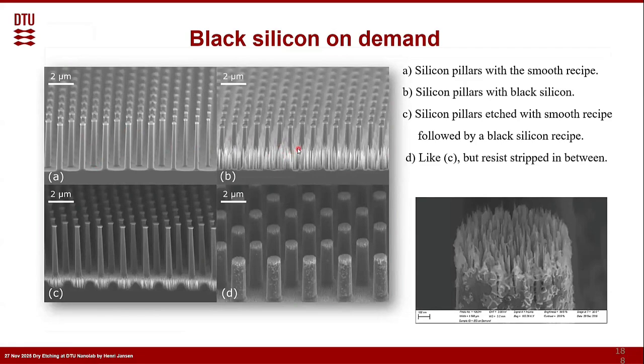You can also say, okay, in the beginning, I etch very nicely. And then suddenly after a while, I switch my plasma to create, at the bottom, let's say, black silicon. What you can also do is that meanwhile, after doing a certain etch, I clean the top, the resist, removing it, and then the silicon on the top will also create black silicon. So you can more or less play with your tool to say, I would like to have roughness on the top, or I would like to have roughness everywhere. You can say wherever you want.